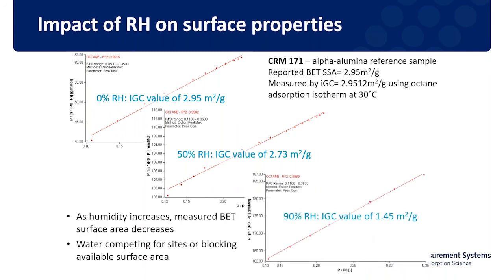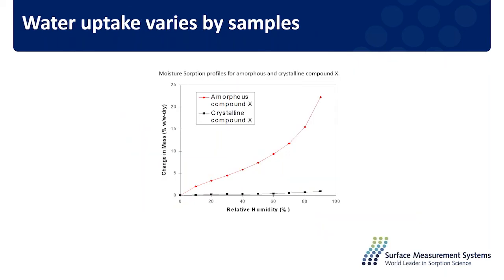Using the standard alpha alumina sample at 0 humidity, the surface area is exactly as the reported surface area. But as we use background humidity in the column, first 50% and then 90%, you can see decreases in surface area, because water will adsorb on the surface and block the available sites. It doesn't mean that if there's humidity, your solid will completely dissolve in water. How much water is adsorbing on your solid surface depends on your solid.